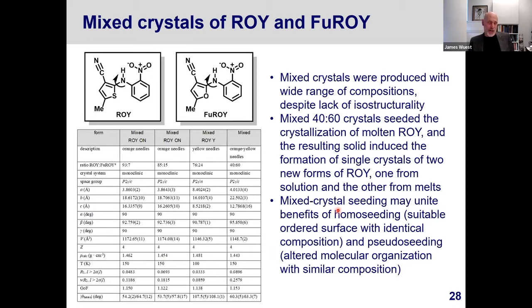That offers a suggestion that there may be something special about mixed crystals. And this needs confirmation, but our working hypothesis is that mixed crystals have surfaces that have a composition that's similar to that of the target compound, but some differences in the arrangement of the molecules that may allow them to have the effect of heteroseeds with different compositions and different arrangements. So that needs to be tested.